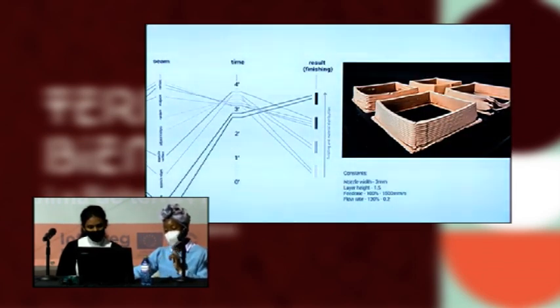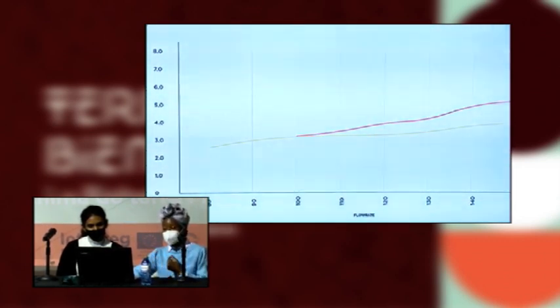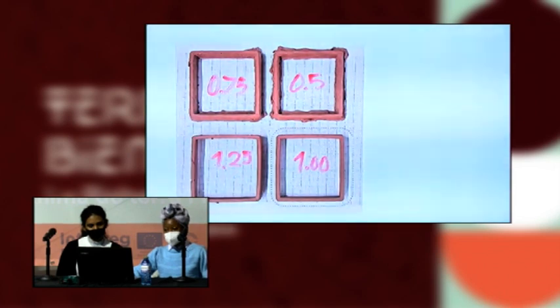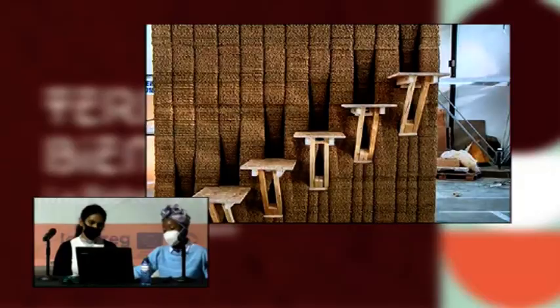The tool path direction, we found the spiral connection is best when you start the print and you end. In terms of nozzle diameter, it works sort of congruently. The bigger the nozzle size, the larger the print of the layer. Lastly, we found a 2:1 proportion. So for every nozzle size, you would create a layer height that is half the width in order to achieve a good print. And these are the conclusions we made in terms of material.